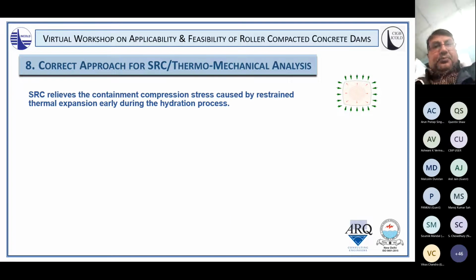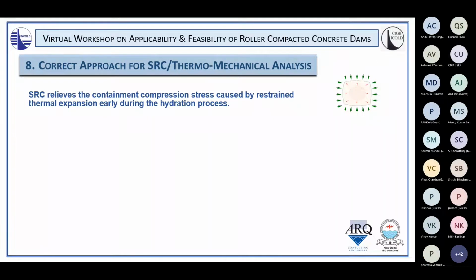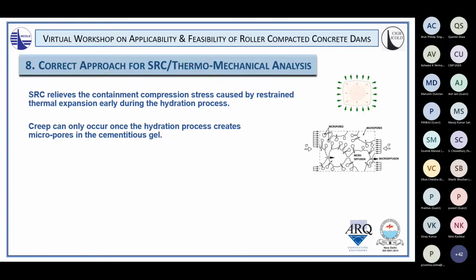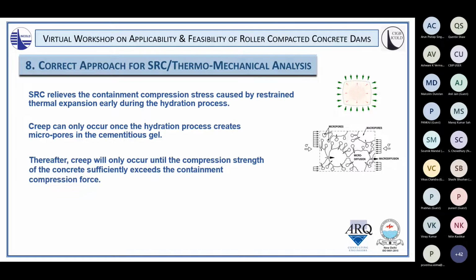Now, raising all these issues about stress relaxation creep and thermomechanical analysis, we need to really talk about what is the correct approach for stress relaxation creep and thermomechanical analysis. Stress relaxation creep relieves the containment compression stress caused by restrained thermal expansion early during the hydration process. And creep can only occur once the hydration process creates micropores and macropores in the gel to allow the migration of moisture. Until that point, it's basically like compressing a fluid. But thereafter, creep will only occur until the compression strength of the concrete sufficiently exceeds the containment compression force.